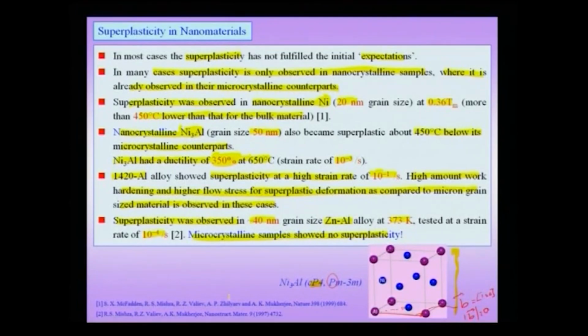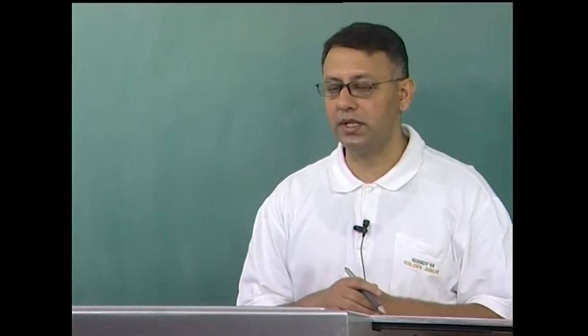So, this is another very interesting example, and now we have covered a gamut of all the possibilities. We have covered pure materials like nickel, we have covered intermetallics like Ni3Al, we have talked about alloys like zinc aluminum alloy and 1420 aluminum alloy. We have seen that superplasticity does take place in one of these cases at high strain rates. In a couple of these cases, you observe superplasticity at much lower temperatures, and additionally you also observe superplasticity in cases where there is no superplasticity in the bulk counterpart. So, this is a very interesting gamut of possibilities when it comes to superplasticity of nanomaterials.